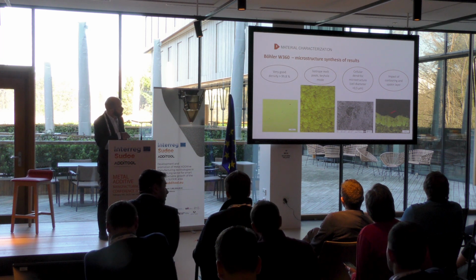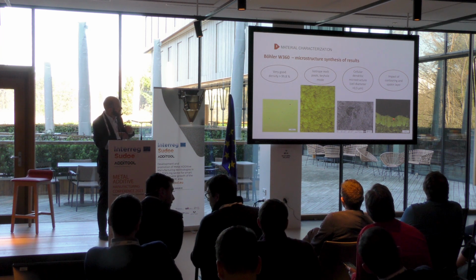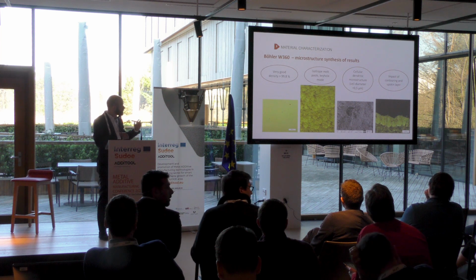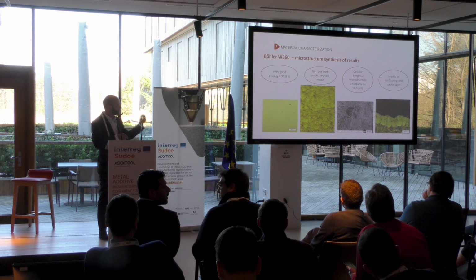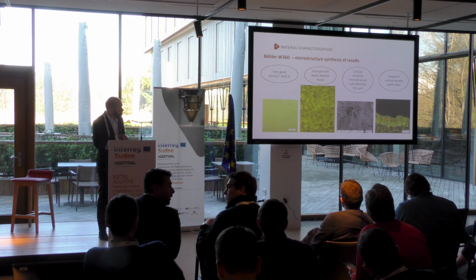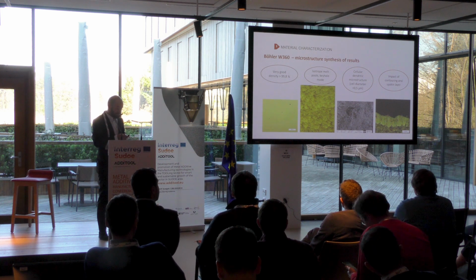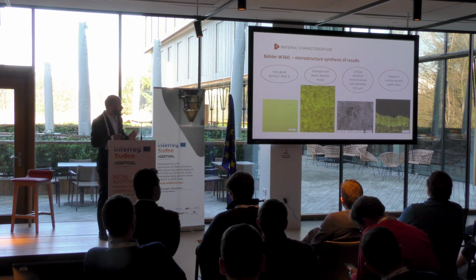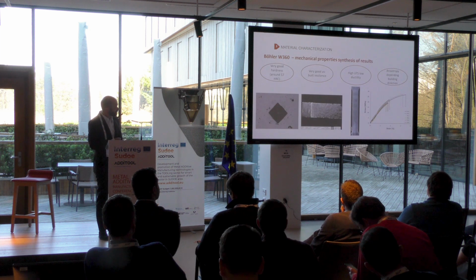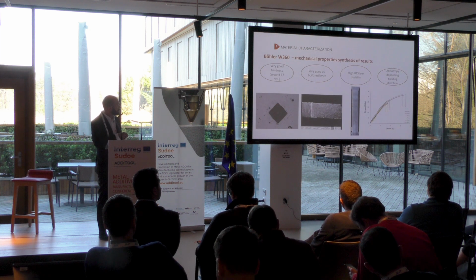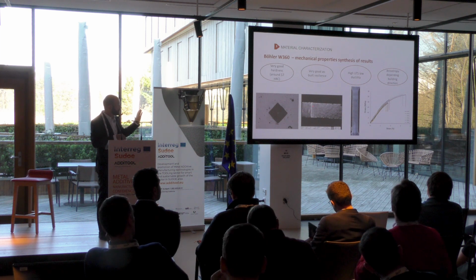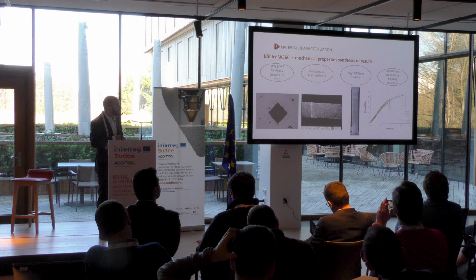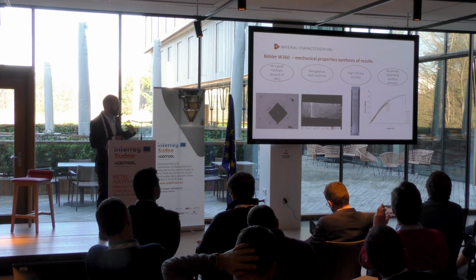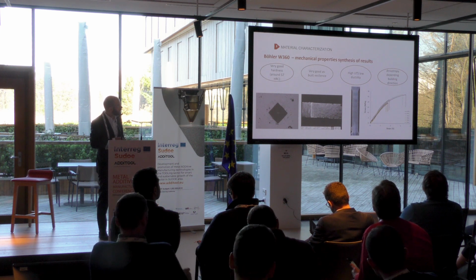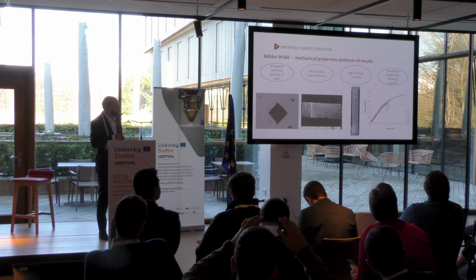And ENIT also noticed that the outer layer presented a different microstructure from the rest of the bulk material, and we also have some micro cracks there, which were apparently not very problematic. In terms of mechanical properties, we have a very high hardness, very good resilience with no heat treatment, high ultimate tensile strength and low ductility. It's a tool steel, and there is some anisotropy depending on the building direction.